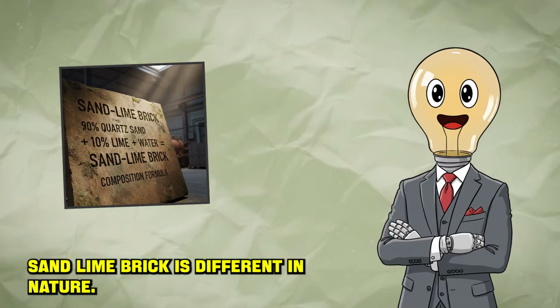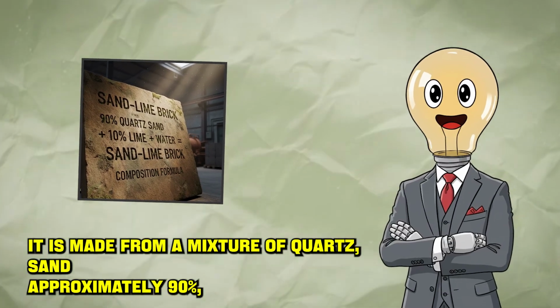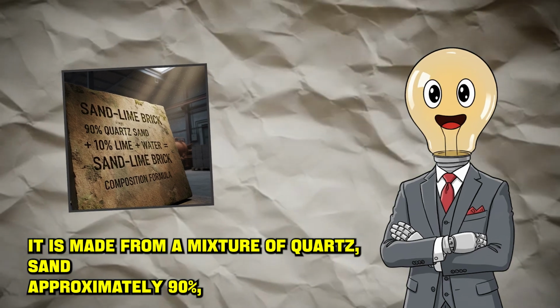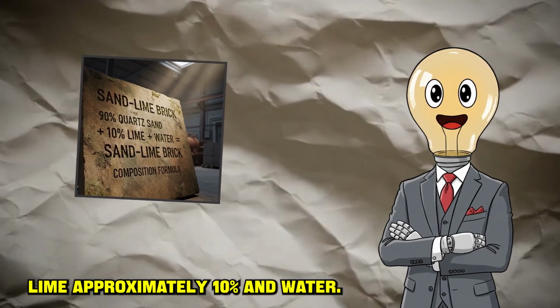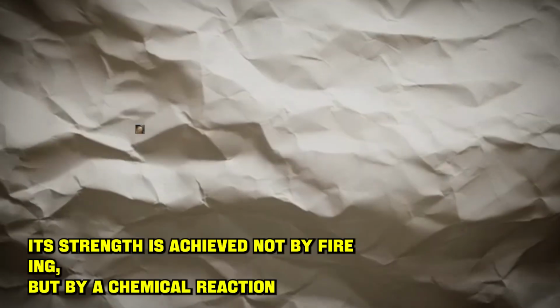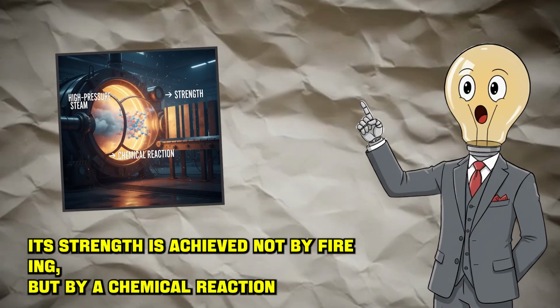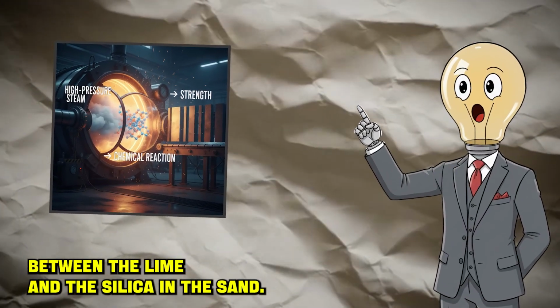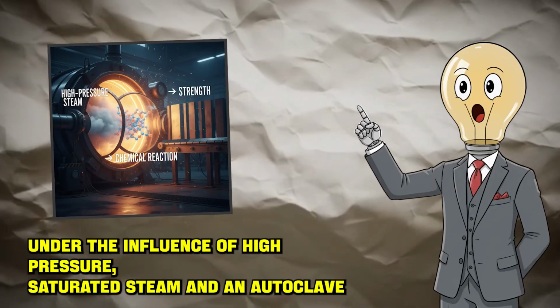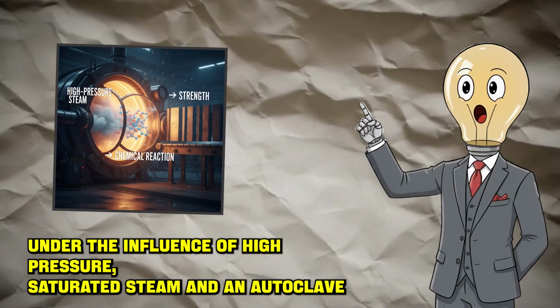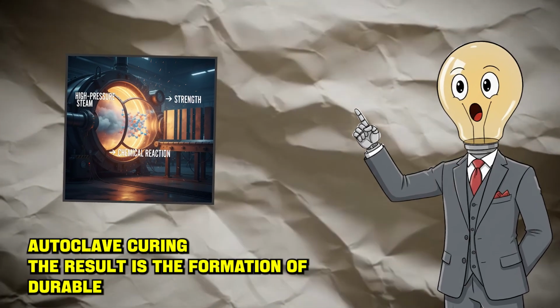Sand-lime brick is different in nature. It is made from a mixture of quartz sand, approximately 90%, lime, approximately 10%, and water. Its strength is achieved not by firing, but by a chemical reaction between the lime and the silica in the sand, under the influence of high-pressure saturated steam in an autoclave curing.